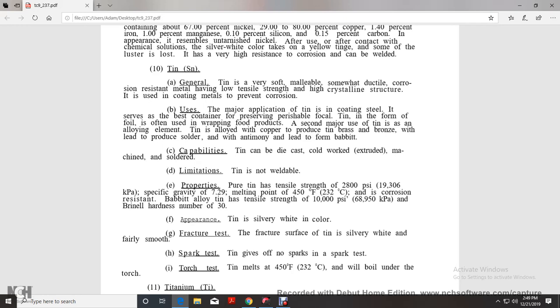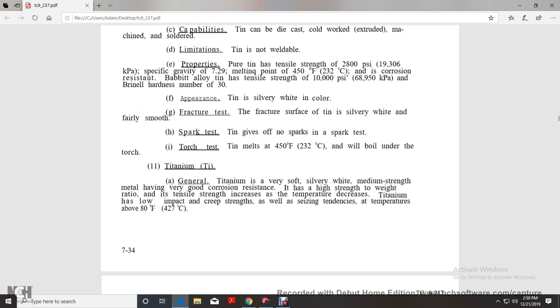Limitations: tin is not weldable. Pure tin has a tensile strength of 2,800 psi, specific gravity of 7.29, melting point of 450 degrees Fahrenheit, and is corrosion resistant. Babbitt alloy tin has a tensile strength of 10,000 psi and a Brinell hardness number of 30. Appearance: tin is silver white in color. The fracture test: the fracture surface of tin is silvery white and fairly smooth. Spark test: tin gives off no sparks in a spark test. Torch test: tin melts at 450 degrees and will boil under the torch.